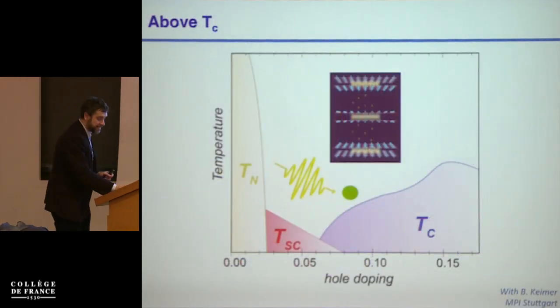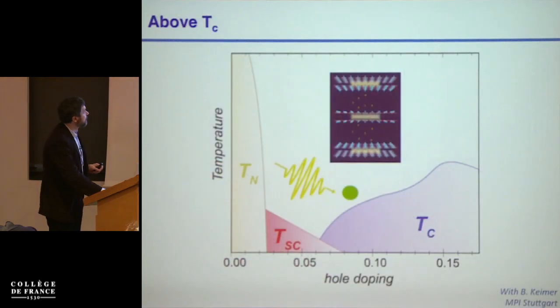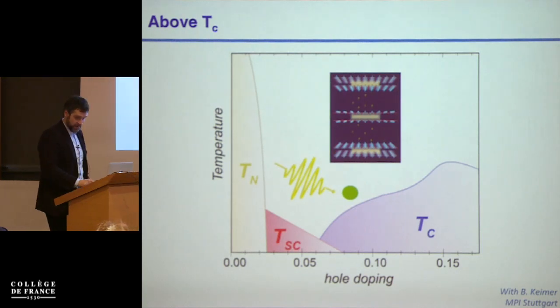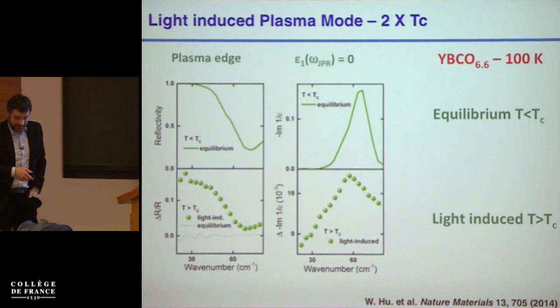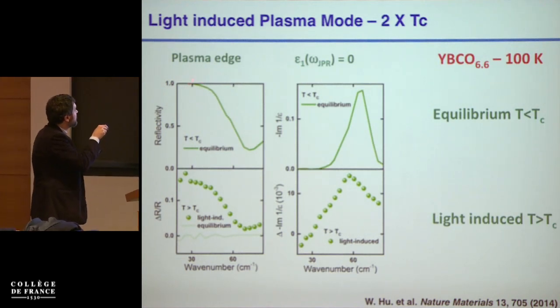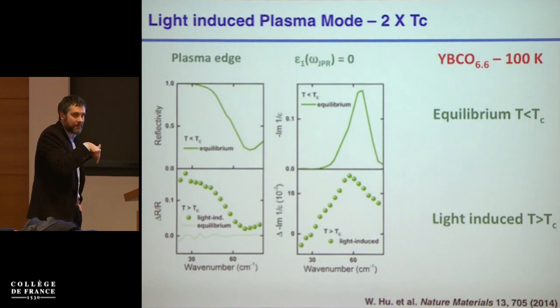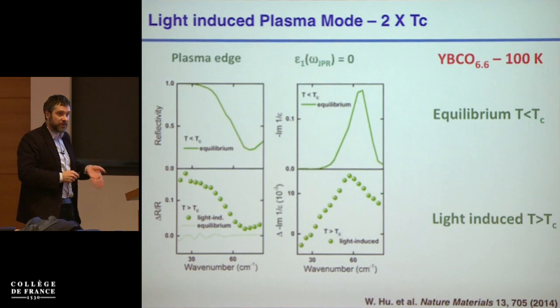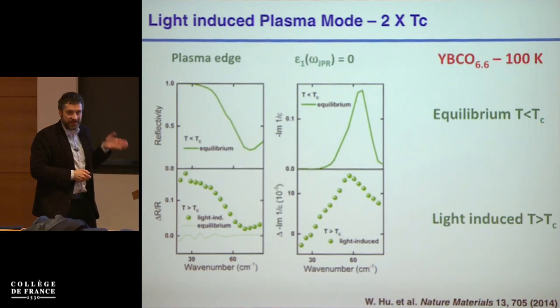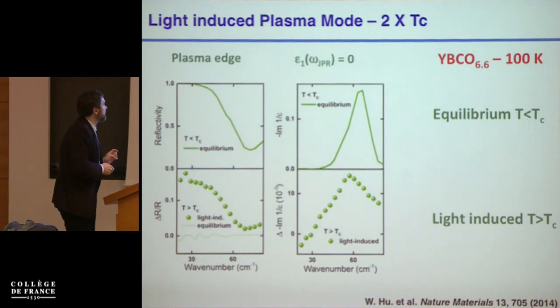Okay, so this was now below TC. Above TC, you go in this state in which there is no tunneling between the two junctions. You excite the apical oxygen, and what you observe is, so now below TC, we observed an equilibrium plasma edge at this frequency, and the loss function, which is the inverse of epsilon1, peaked at the same frequency. When you photoexcite this, you observe an edge exactly at the same frequency which you observe below TC in the same compound, and you observe a peak in the loss function exactly at the same place, indicative of the appearance, like in the LESCO case, of transport with very high mobility at the same density as the transport given by the Cooper pairs below TC. Okay?